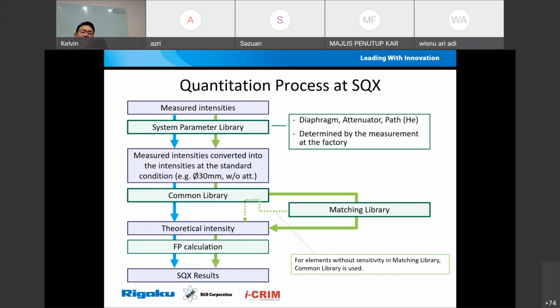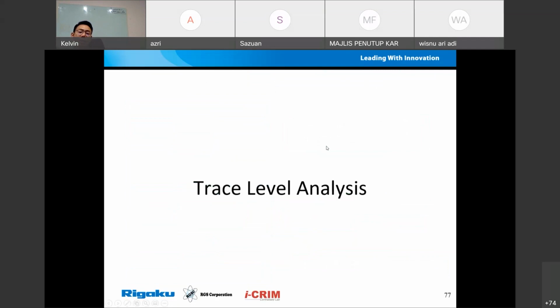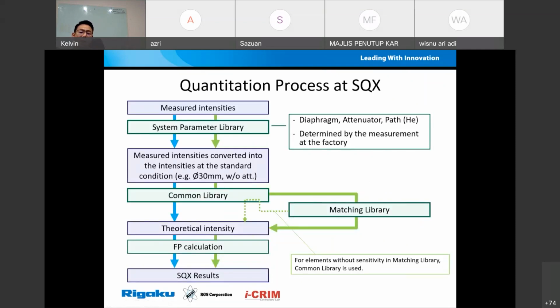In the Rigaku software, another thing is that even though it is called standardless analysis, it has a so-called common library, which is pre-measured intensity inside the system. So when it calculates, it uses the common library. But in the Rigaku software, you can also add additional standards, where you input a so-called matching library to improve your standardless calculation according to the standards that you put in there. That means you can have just one or two standards inside your system to improve the standardless analysis. So this is the quantification part of the system, where you have empirical calibration and also standardless measurement.